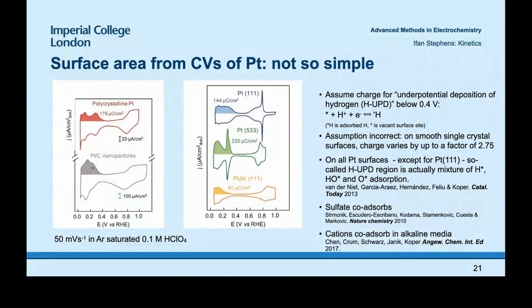So even if you look at very single crystal surfaces, for example platinum 111, in this region where hydrogen absorbs, or where we think hydrogen absorbs, the charge varies enormously depending on the surface. If you look at platinum 111, this is an atomically smooth surface, remember? You have about 144 microcoulombs per centimeter squared in this region. On a stepped platinum surface, it's 220 microcoulombs per centimeter squared. And then on an alloy surface, this is a platinum nickel alloy, but the surface is pure platinum, you have 80 microcoulombs per centimeter squared. Even though the actual surface area is always the same, the charge varies enormously, by up to a factor of 2.75. So this assumption that this charge is independent of the surface termination is not actually correct.